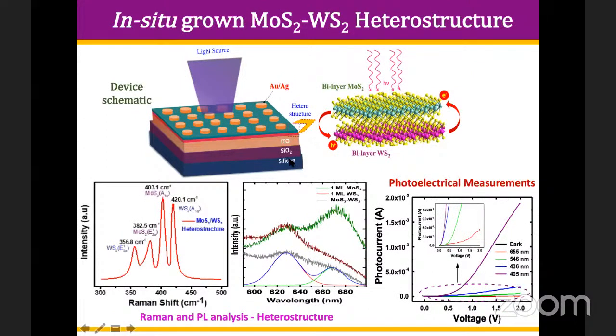And by using this, we try to make the heterostructure of WS2 and MoS2. So WS2 is here like this, and MoS2 is here. Both these heterostructures we put over the ITO, and for the top electrodes we use gold and silver. You can see the Raman spectroscopy of this heterostructure, where we got the peaks of both WS2 and MoS2. These are the PL spectra of one monolayer of MoS2 and one monolayer of WS2, and this is the PL spectra of the composite. You can see the heterostructure having the peaks of both, and then the photocurrents we obtained for different wavelengths for this heterostructure, and I will give you detail in the later slides.